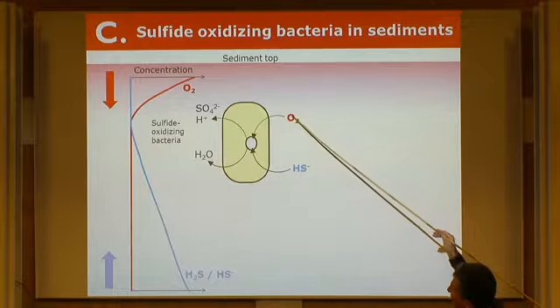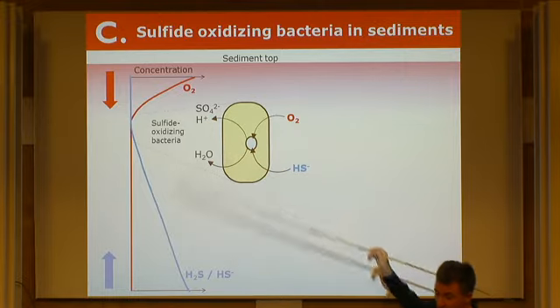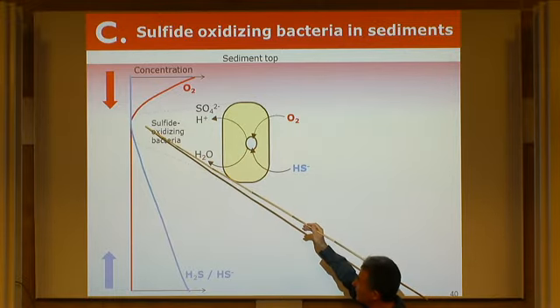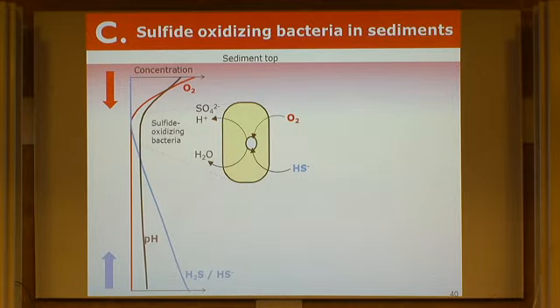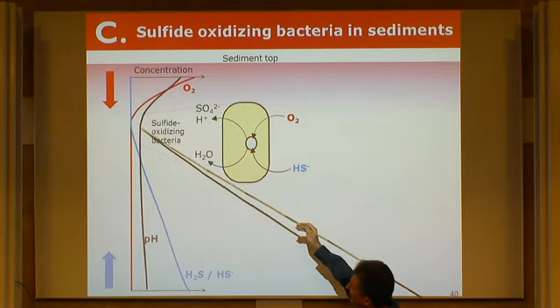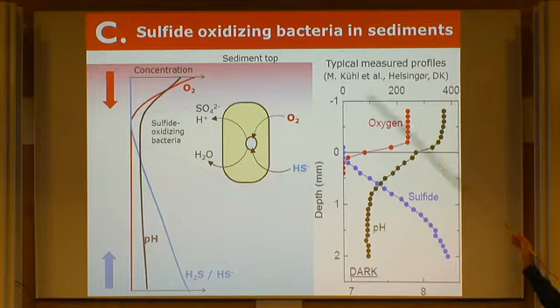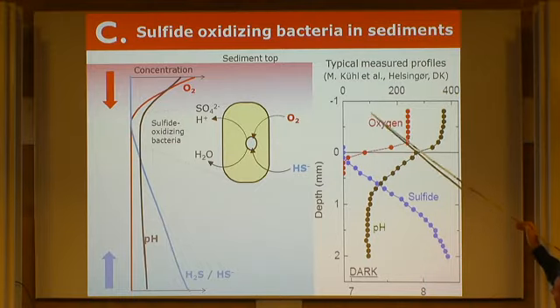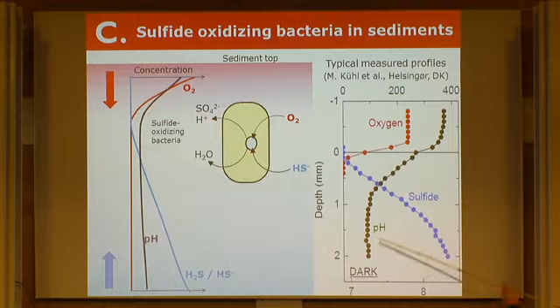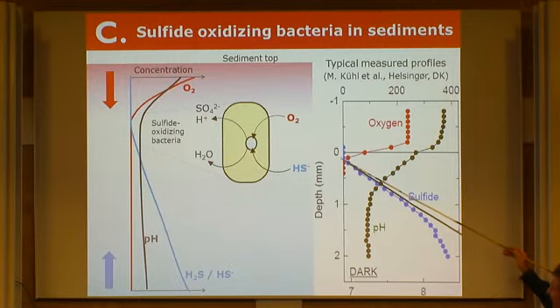You know, this is sulfide, oxygen, produce sulfate, produce protons, which means that you should have some acidification here. And that's why the pH should somehow drop a bit. And this is actually what people measure. Michael Kuhl in Denmark, for example, always uses this kind of electrodes, the oxygen electrode, the pH, the sulfide, to measure these gradients. So this is another typical counter-diffusional system. Oxygen from the bulk liquid, top of the sediment, sulfide coming from degradation from the bottom. And they meet here, and here is where sulfide oxidizers grow. Okay, that would be the typical example.